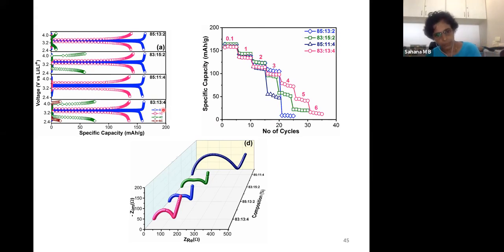The meaning of 0.1 C is, once we prepare a cell, if you say, for example, a 30 milliampere hour cell we prepared, the full nominal capacity of the cell is 30 milliampere hour. Now, if you discharge that in 10 hours, that is 0.1 C. Whereas if you discharge that in 1 hour, it is 1 C. So you are applying a higher current when you charge or discharge it at 1 C. Now, if you charge or discharge it in 1/6 of an hour, it is 6 C.